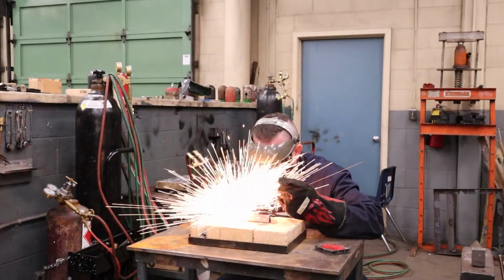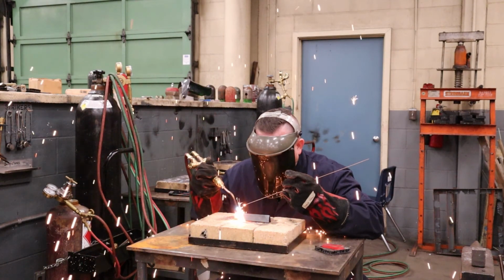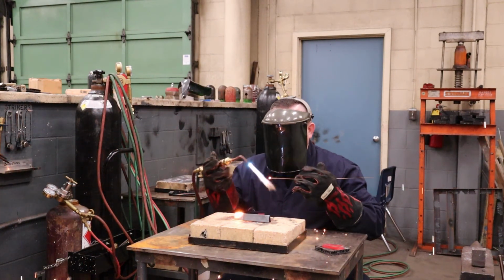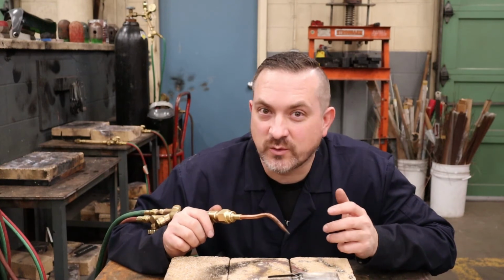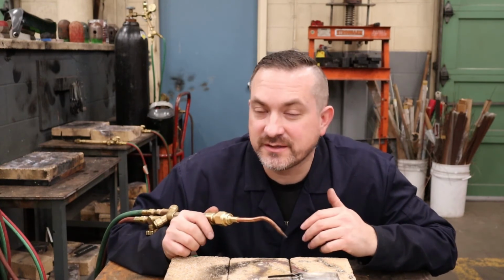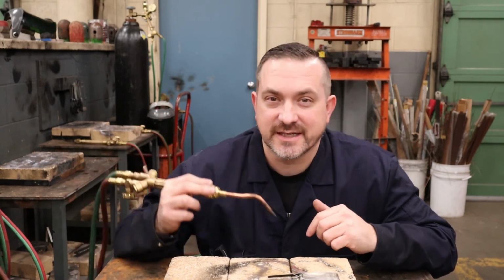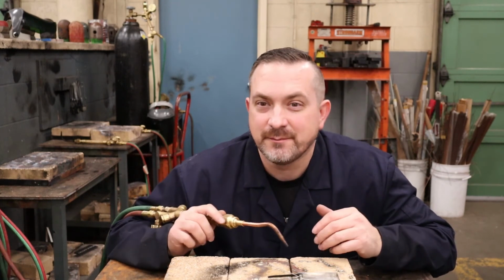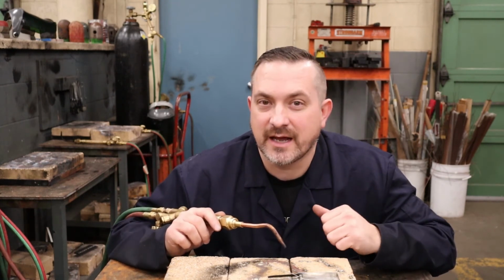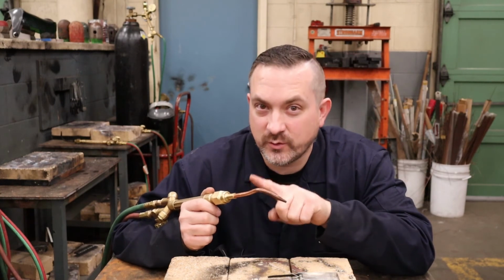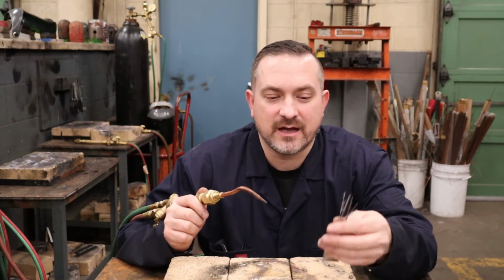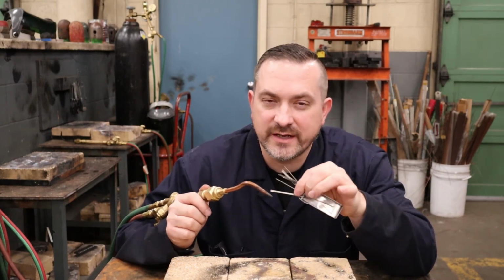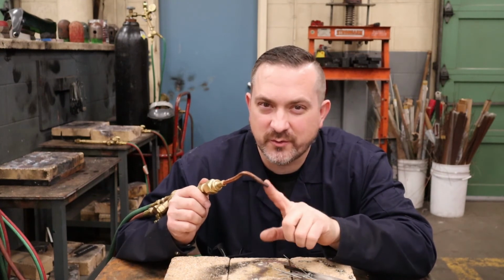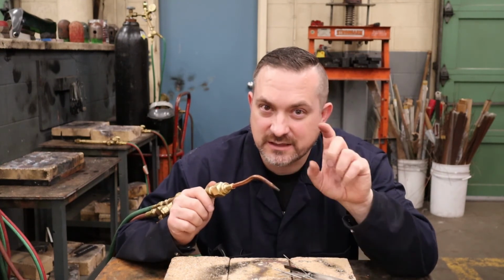That's a pop. If you're having some issues with popping during gas welding, there's actually a long list of things it could be, so let's run through them. First thing, take a look at your regulators. That's an easy one. Make sure that both gases are flowing at whatever they should be for the welding tip that you have picked. Second thing, I would get yourself a set of tip cleaners and really clean out that orifice. Make sure there's no debris in there that is blocking proper gas flow.